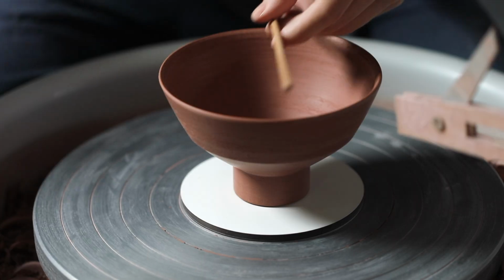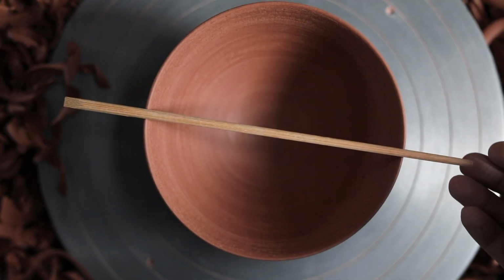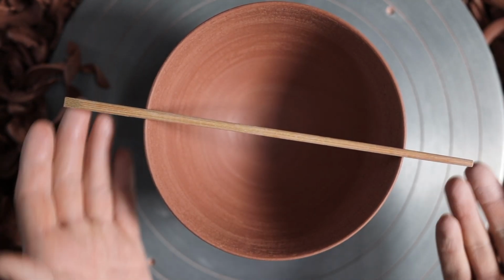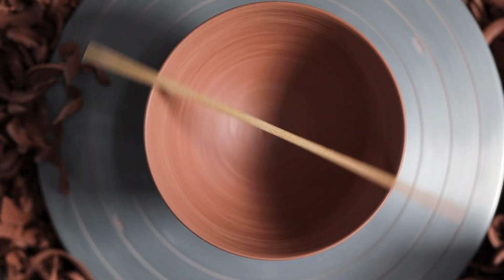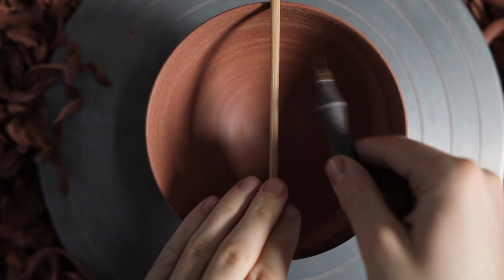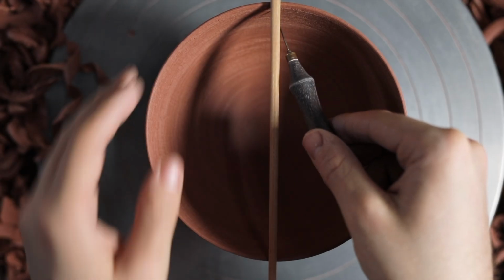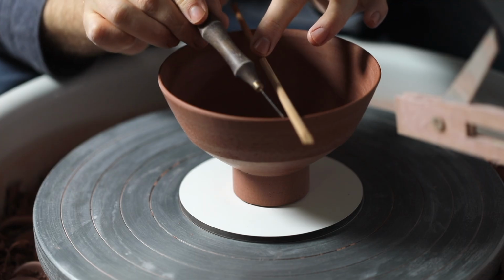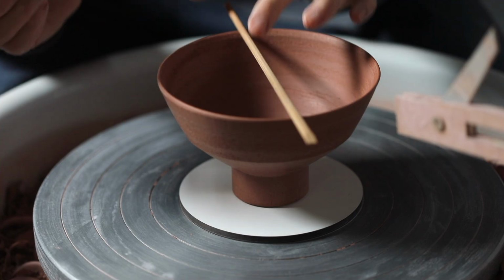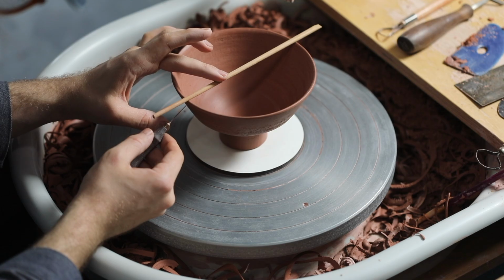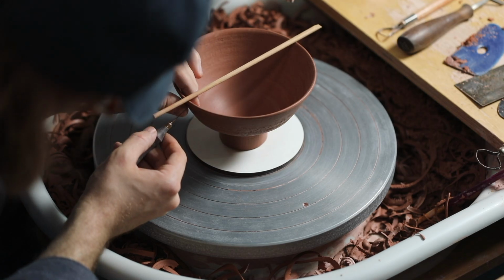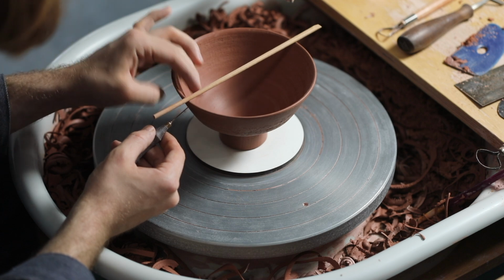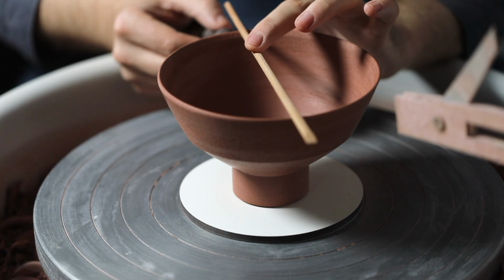I start by laying a guide across the top, a chopstick in this instance, as it's soft, light and rounded, so it shouldn't damage the rim at all. I then use a potter's needle to create two small marks, one on the inside of the rim and one on the outside. I'll try my best to insert the bronze into these pinpricks, but it doesn't matter if it's not completely accurate, as these fragments of metal will bloom where they're put, creating much larger marks compared to their size.